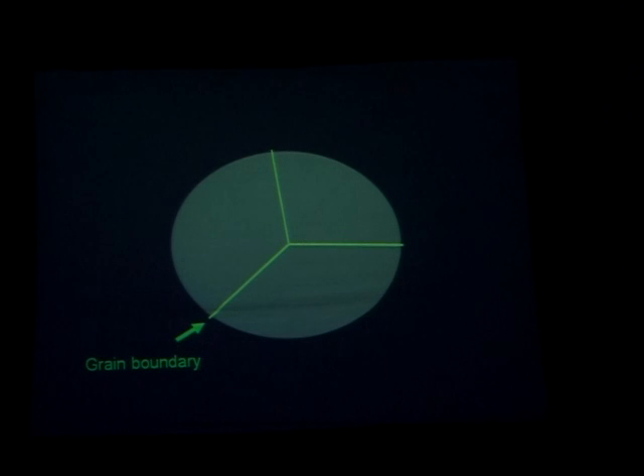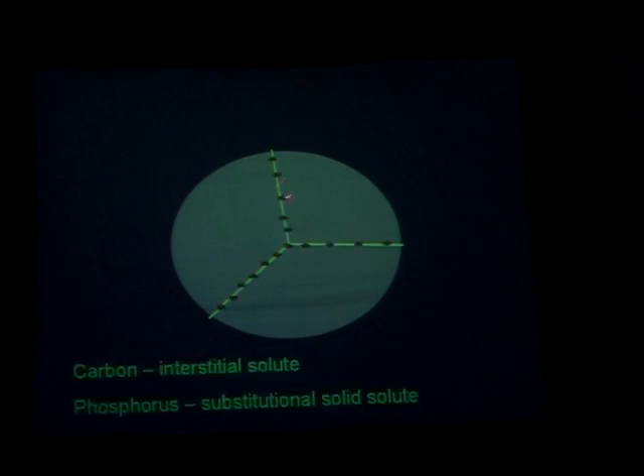And of course, the basic idea is that in order to prevent embrittlement, you add a small amount of carbon and control the microstructure. How? Here is the idea of carbon addition. You take a grain boundary and put carbon in that. Once you put carbon here, phosphorus will not get here because carbon is interstitial. It will repel phosphorus, a substitutional solid solute.